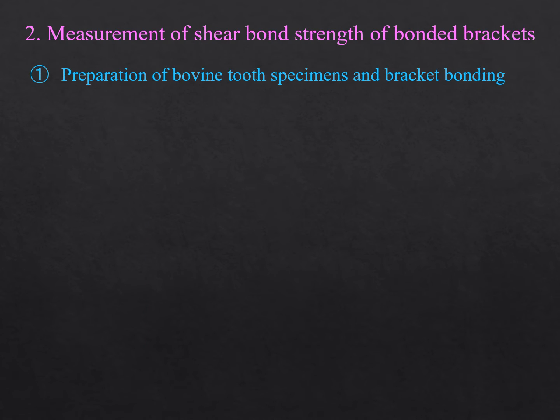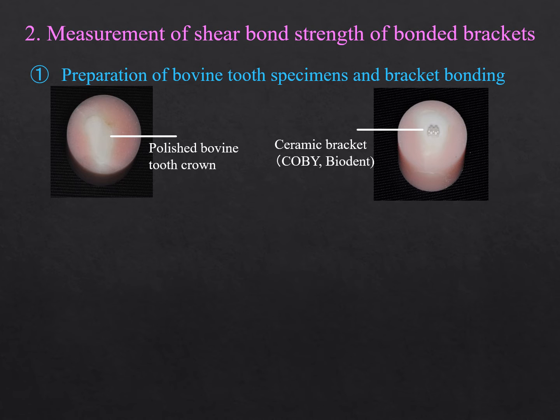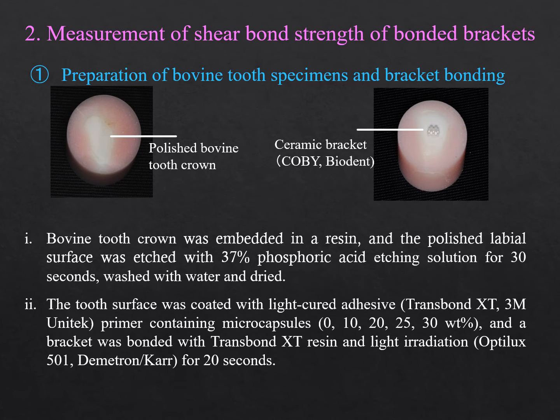The preparation of bovine tooth specimens and bracket bonding. The bovine lower mandibular incisor crown was embedded in a resin, and the polished labial surface was etched with 37% phosphoric acid etching solution, as instructed by the manufacturer, washed with water and dried. The tooth surface was coated with light-cured adhesive primer containing microcapsules, and the bracket was bonded with Transbond XT resin and light irradiation for 20 seconds.